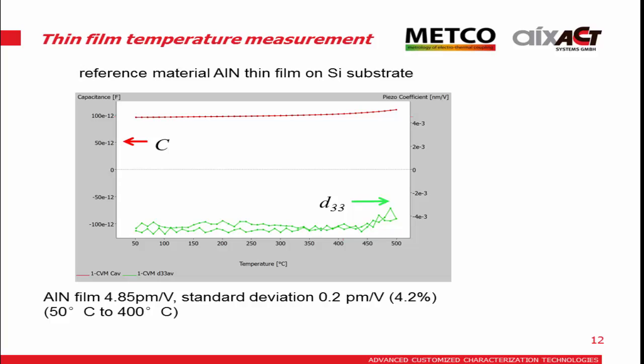But it's stable, and we showed that it's, in this case, stable up to 450, and seems to be almost reversible. You can see that the deviation is much higher across the temperature, mainly due to fluctuations. So we have around 4% standard deviation if we take the whole run.